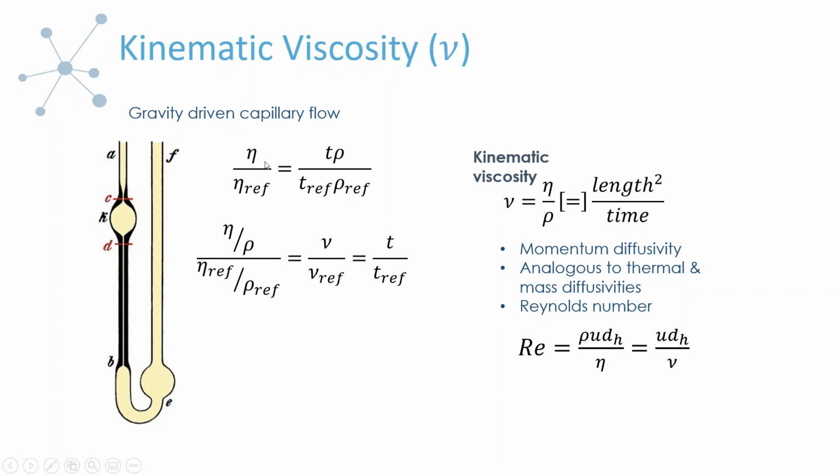And then in order to actually get the viscosity of your sample, say your polymer in that particular solvent, you would just measure the time it takes to drain through the tubing. And if you don't have knowledge of the density of, say, the polymer solution, then the way this can be rearranged is we can divide the dynamic or steady shear or absolute viscosity by the density, and this is what defines the kinematic viscosity.